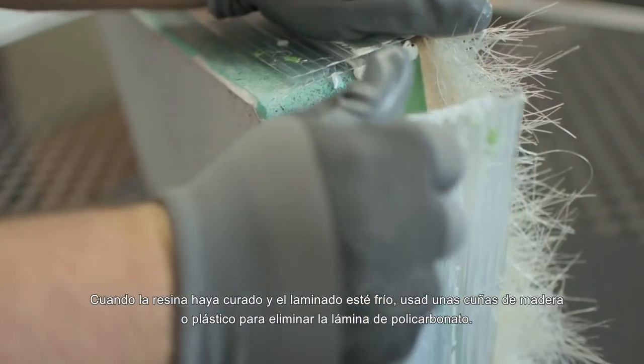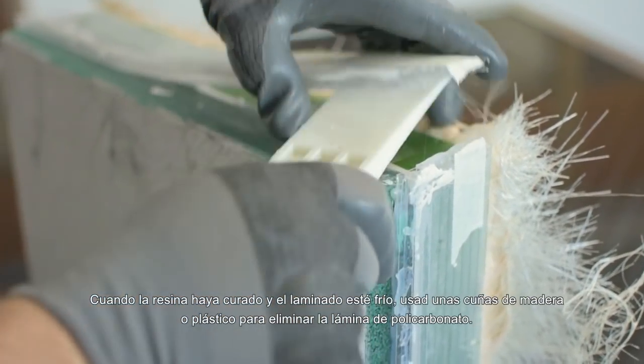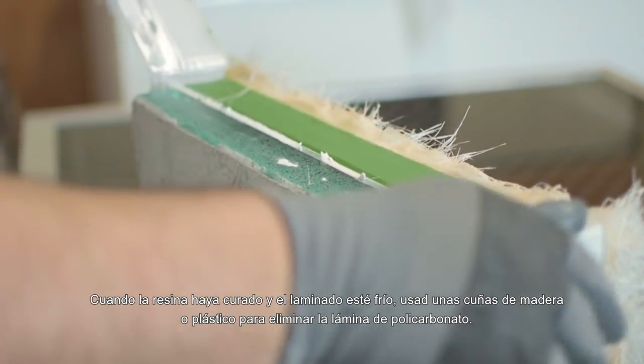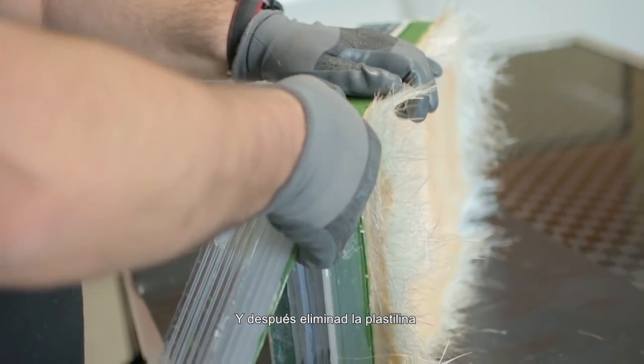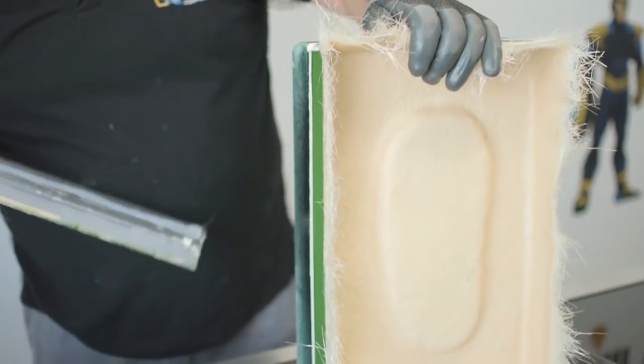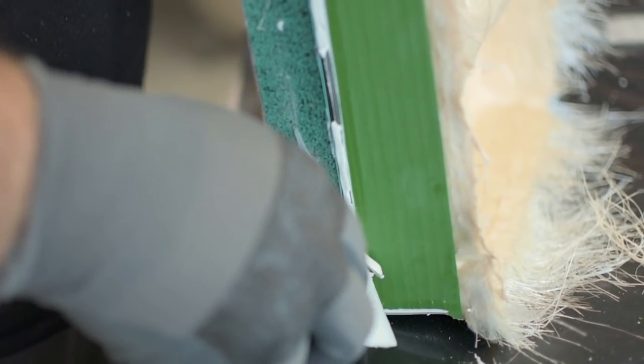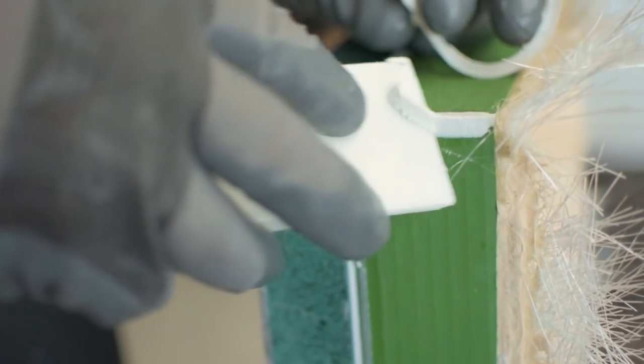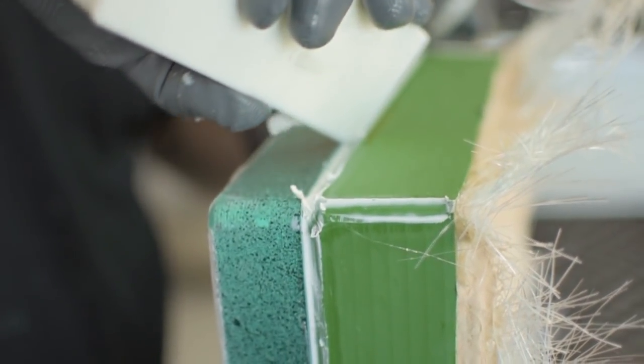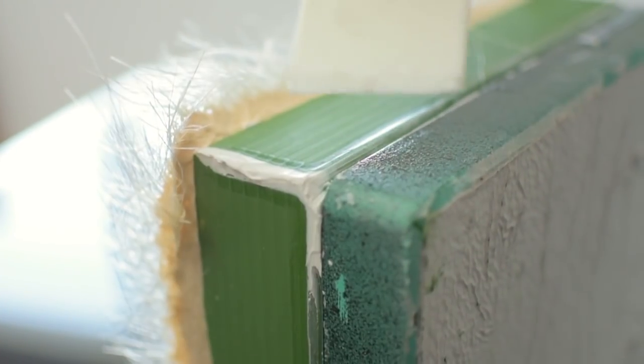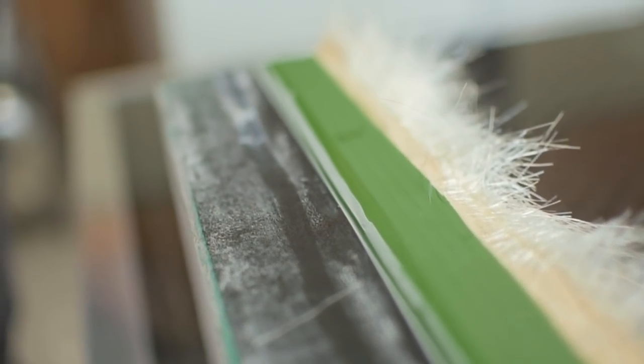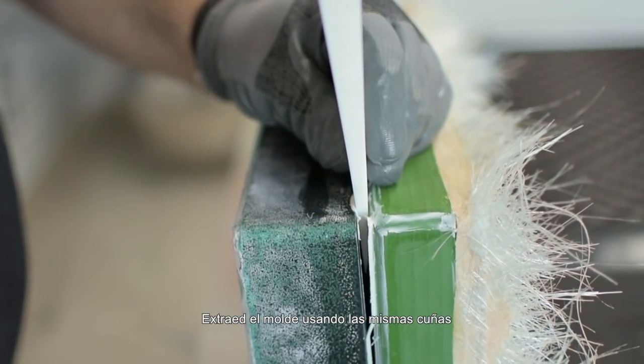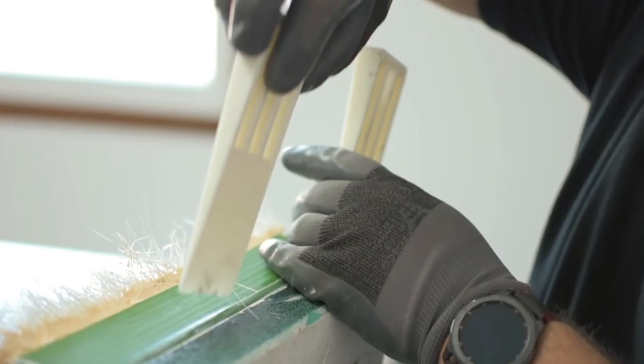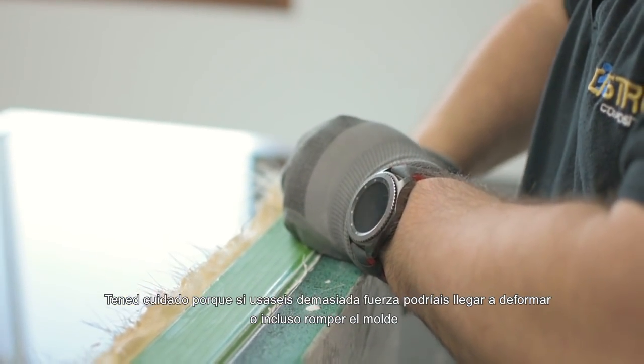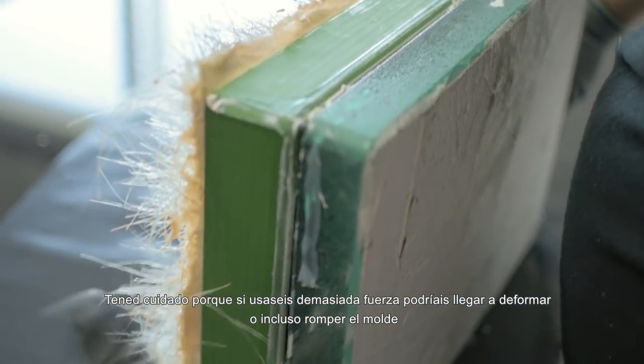Once the resin is cured and the laminate is cold, use plastic or wood wedges to remove the polycarbonate sheet we use in the mold, and also remove the modeling clay. Then, with the same wedges, remove the mold itself. Be careful, because if you use too much force, you can deform it or even break it.